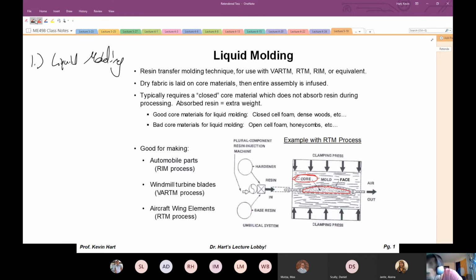And on the outside, you see all these. This is where your reinforcement would go on the outside. Okay, so this is kind of a dry manufacturing process where you place the core inside of the mold and it's surrounded by dry fabric. Then you inject your liquid molding compound into the mold to solidify the resin in the fibrous region, which is the outside dry portion of the core. All right, so that's the general idea here.